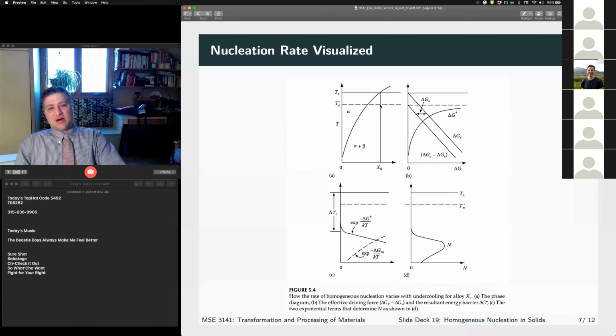But if I come down and I hold at some intermediate temperature, I can get precipitates to form, right? Because I have a finite nucleation rate. Once I get the precipitate structure I want, I can then quench down to room temperature. And because I don't have any more driving force for diffusion, I'm able to lock that precipitate structure into place. Okay? So this is where we really see the difference between thermodynamics and kinetics.